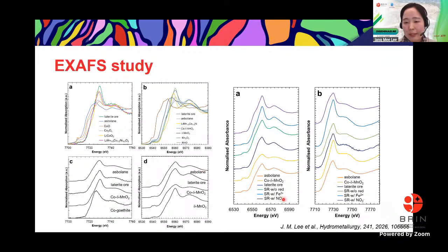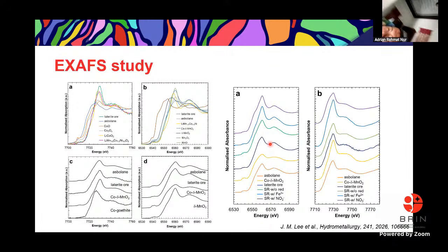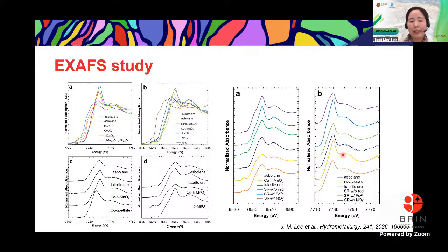And this is the SR. As I mentioned, it is the solid residue collected after the leaching test. After the leaching test, the main spectra remain the same, though I didn't show the result in this presentation slide, but in the EXAFS signal, it shows a slight increase in the disorder factor. So after the leaching, we found the creation of oxygen vacancies and also an increase of the disorder factor.